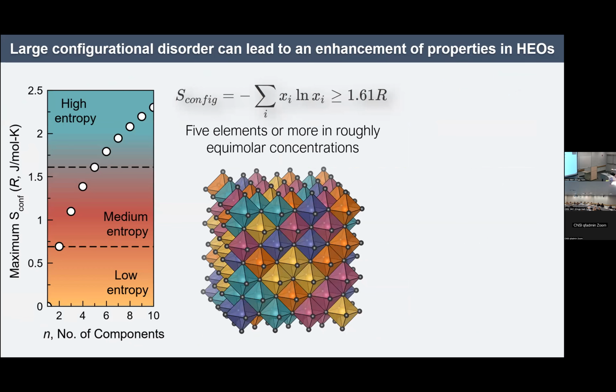Those 2 requirements alone are not entirely sufficient for defining a high entropy oxide, because one class of materials that already fulfills the definition I've given you is a conventional solid solution, any material where I take 2 elements and mix them on a lattice. To deserve the special name of high entropy materials, we would like there to be an additional criterion that distinguishes them from conventional solid solutions. The criterion that has emerged as the most prominent or recognizable is to quantify the configurational entropy that the material exhibits. We can calculate the configurational entropy, which represents the number of different ways I could arrange my different elements onto that lattice.